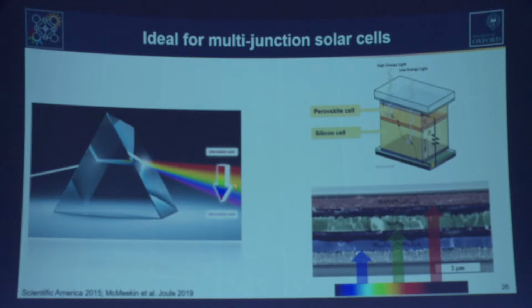But if we take blue photons, they might carry 3 electron volts, so you could generate a solar cell with 3 volts. The red ones carry about 2 electron volts of energy, and out to the infrared it goes down. So the lowest energy photon absorbed by silicon, for instance, is about 1 electron volt of energy, so a silicon solar cell will never give you more than 1 volt in power.